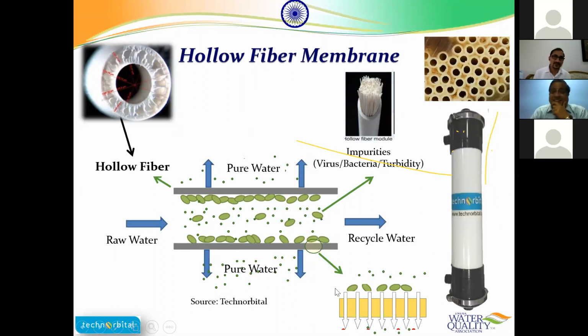The state of the art, the recent membranes, are hollow fiber membranes. These are like tubular membranes, but very teeny tiny tubular membranes. We are talking about maybe 0.6, 0.7 mm outer diameter. You can see the picture in the top left corner. That's the cross section of the hollow fiber under a microscope. The outer diameter is around 0.7 mm, the inner diameter is 0.3 mm, and the wall of this pipe is porous. If you look carefully, both the inner and the outer walls have very small porosities, averaging from 5 to 20 nanometers, and in between we have these big bulbs of 100 to 200 nanometer sizes.